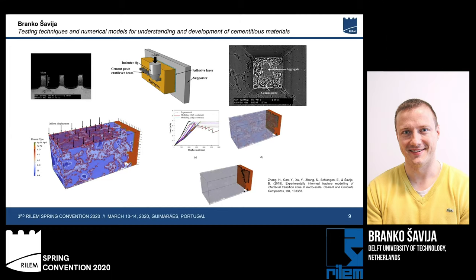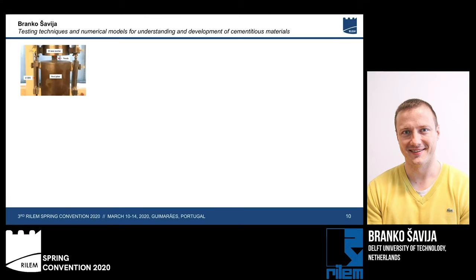So now we go to the higher scale. Higher scale is the mortar scale. As I said, we can do experiments in this scale. In this figure, you can see a very small 10 millimeter mortar specimen with two notches that will be subjected to direct tension. We can also, again, simulate this experiment by creating a microvolume of our material.